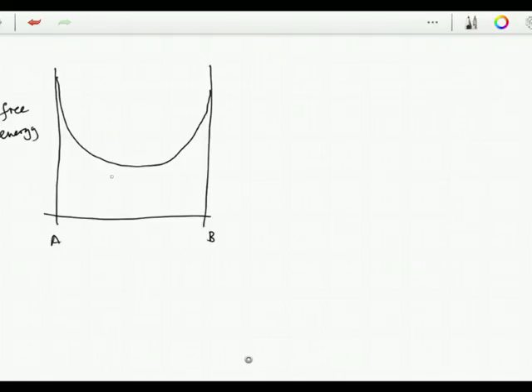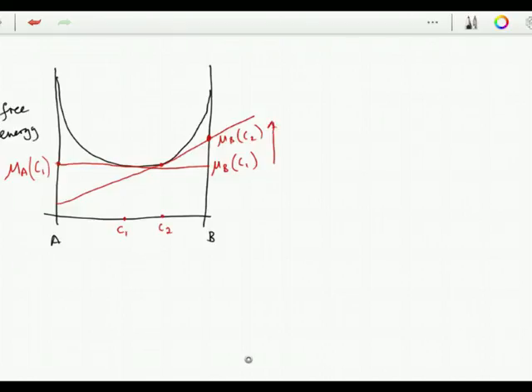Then when I draw a tangent to this curve, which touches at this particular value of concentration, that gives me the chemical potential of atoms A at the concentration C1, and that gives me the chemical potential of B atoms corresponding to the concentration C1. Now, if I increase the concentration, then the chemical potential also increases. So here we have mu B of C2, where C2 is this larger concentration. So you can see that the chemical potential of B has increased. In other words, d mu B by dCB is greater than zero.